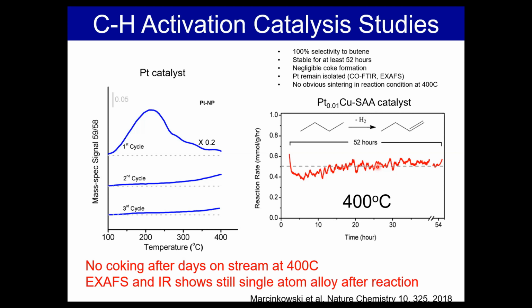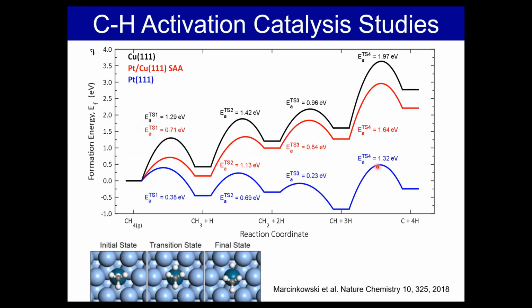do CC coupling. And this is really nicely explained by Mavrikakis' group, where they plot out the energetics going from methane, methyl, CH2, CH, carbon. On platinum, that is exothermic to form carbon on platinum. So that's why platinum catalysts will coke. Whereas these single atom alloys, the red line here, will reduce the CH activation barriers, but it's endothermic to coke. So you can basically go over the first step or two and then no further, which gives you